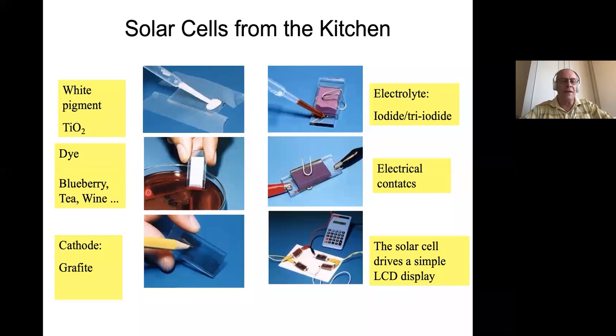That's the negative, the minus electrode in our solar cell. We need then the plus, and that's simply made by putting some pencil, the graphite, on the other contact. And you put the two and clamp them together, and then you bring in the electrolyte, which shuttles the charge between the contacts. And you're ready to attach your crocodile clips, shine light on it and measure the current and potential electricity you get out.